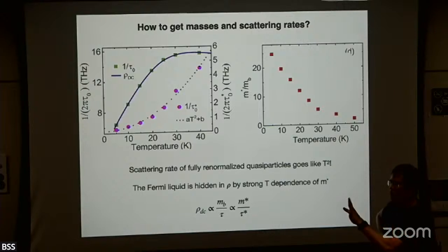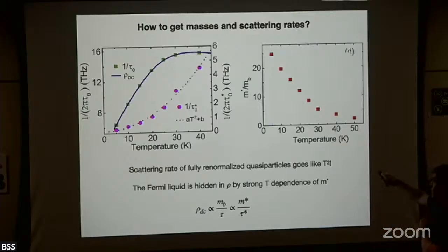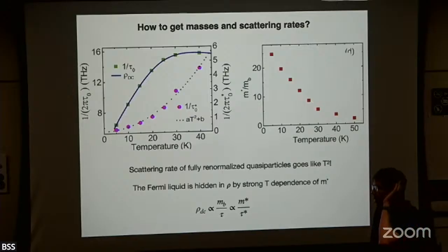Yeah, roughly that's what's going on. That's right. I wouldn't say that it's not; approximately that's true. The single-ion Kondo temperature, I don't remember, but the Kondo lattice temperature you can pull out from this peak, which is something of order 30 or 40 Kelvin.